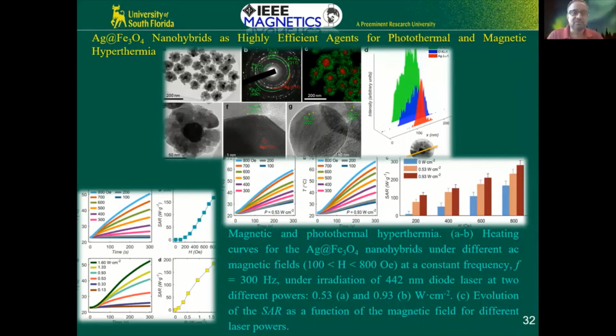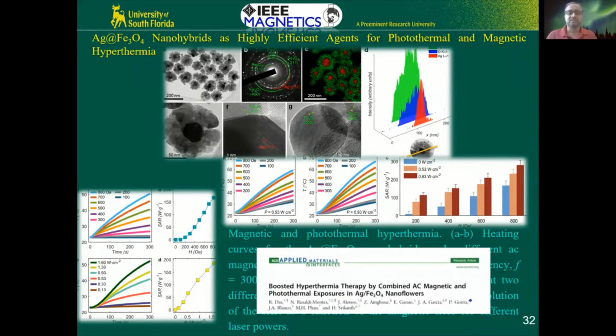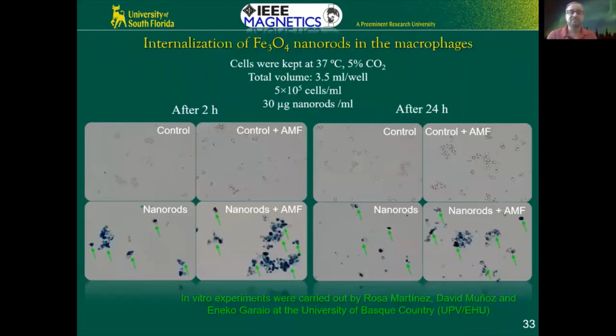Also, hyperthermia or heating is not only for magnetic particles, you can also heat up gold particles. If you make 10 nanometer gold particles, you can induce the so-called surface plasmon resonance, and by shining a laser at the right frequency, you can cause gold particles to heat up. So you can do the heating both by magnetic hyperthermia and photothermal hyperthermia. We showed that by combining the two functionalities of heating, we can do much better than just the magnetic heating itself. So again, these are some examples of different types of hybrid nanostructures that involve interfaces.